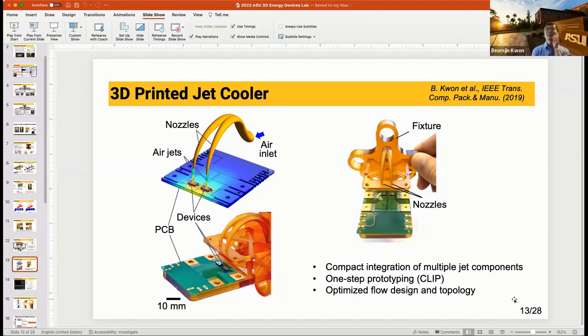Oh yeah, actually I didn't really elaborate on how we optimize. Basically, we simply considered a steady state operation, not transient operation. I found that for jet cooling, the spacing between the nozzle exit and the heated surface is quite critical, and also the length of the nozzle. The length of the nozzle determines the flow state, so you must have sufficient length in order to achieve fully developed turbulent flow.